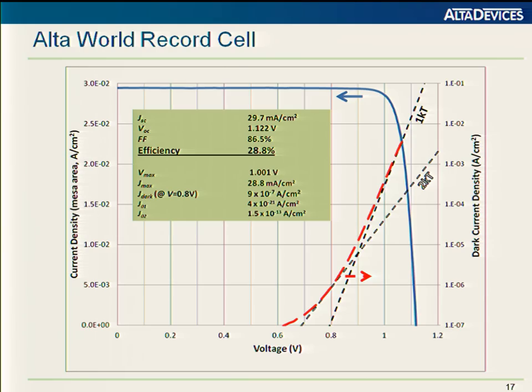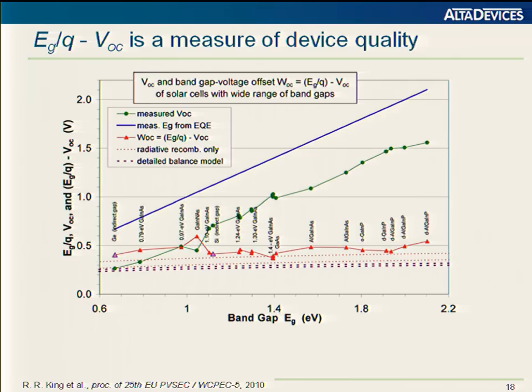So boosting the VOC comes as a product of reducing the dark current. We believe we have achieved lower dark currents in this device than have been seen before with gallium arsenide. I think that's an important point, that you're really changing the way the structure communicates optically with its environment, whether it's in the light or in the dark. If you think about a detailed balance model, the cell has to emit a certain number of photons to be in equilibrium with its environment. And so the more efficient it is at emitting light, the lower the dark current can be.